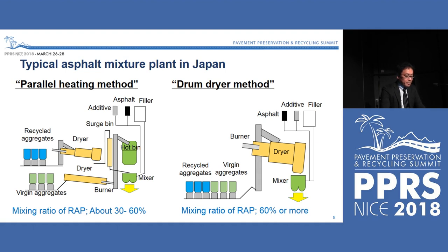For this type, the mixing ratio of RAP used in a dense graded asphalt mixture reaches between about 30% and 60%. An illustration of the drum dryer method is shown on the right. This method mixes RAP and virgin aggregates in the same dryer. The drum dryer method is the most capable of increasing the ratio of RAP in the recycled asphalt mixture. For this type, the ratio of RAP can reach 60% or more. It's mainly used in the Tokyo metropolitan area, but it's used only about 10% of all.